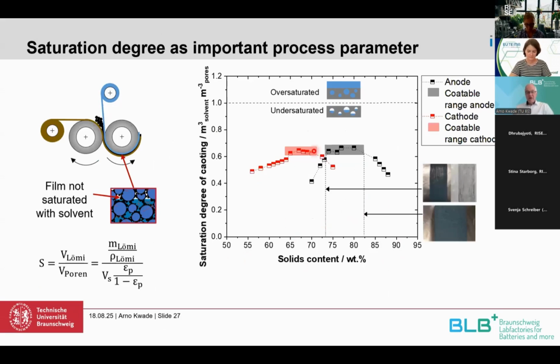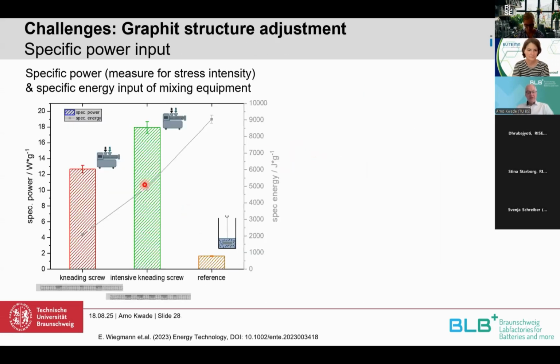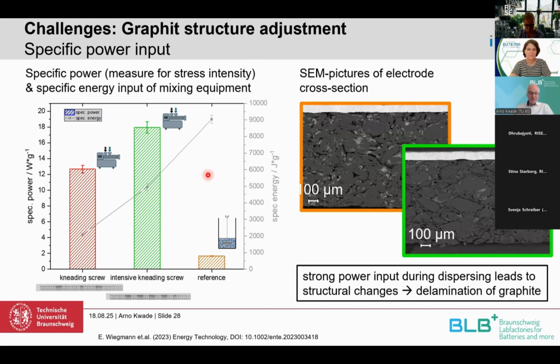What we found is that the saturation degree of the granules is very important to get a good result. About 60% of the pores are saturated, so filled with liquid, and 40% is air, which gives us a good possibility in the following. When you compare different extrusion screws, you can see that by making the screw more intensive, you get a higher specific power input to the suspension, or the wet powder, compared to the wet process on the right side. But at the end, the specific energy requirement is much lower with a kneading screw, a little bit higher for the intensive kneading screw, but for the reference, because you need a much longer time, the specific energy input is by far the highest.